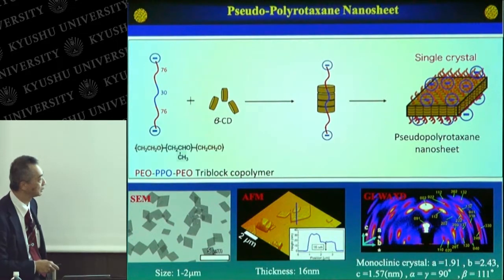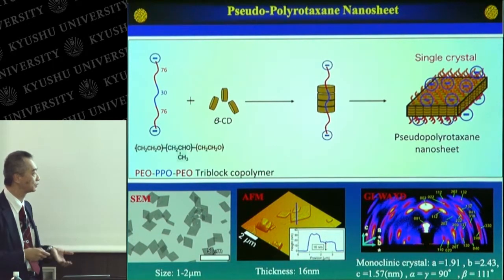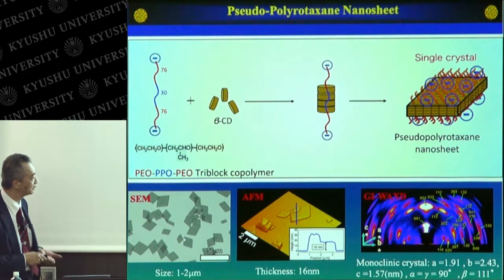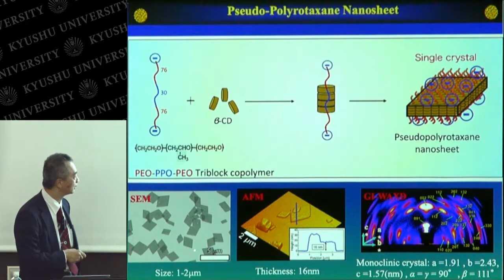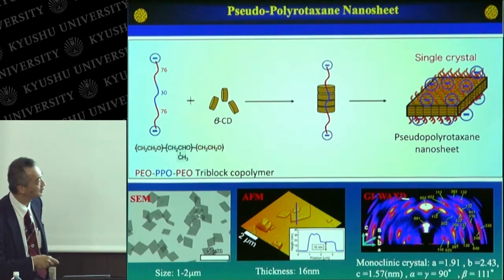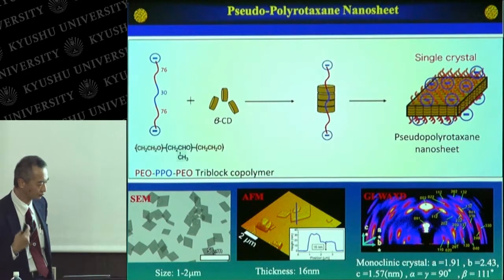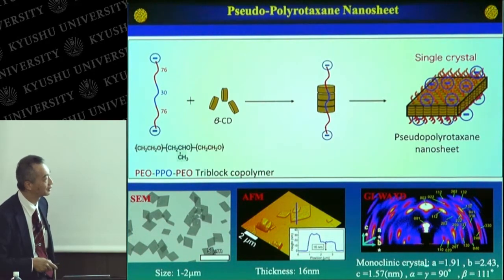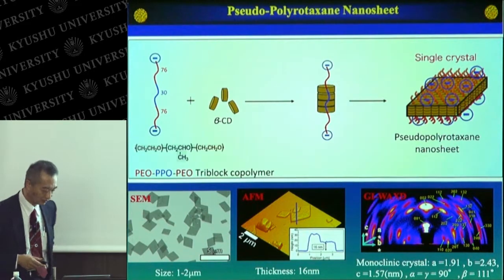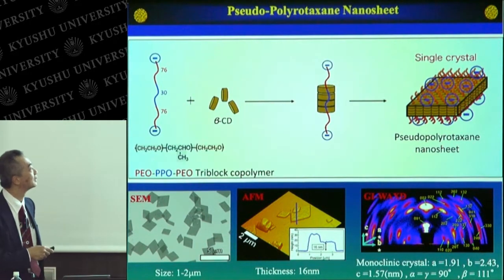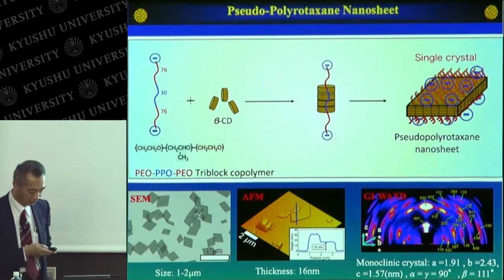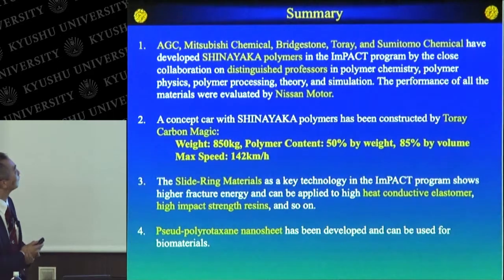You can see that this nanosheet has a thickness of 16 nanometers. It's dispersed in the water, and the size is about 1 or 2 micrometers. And you can see this nanosheet has this shape. So this shows the X-ray diffraction results of this nanosheet. It shows a single crystal, and it's very simple. It's a very complete monocrystal nanosheet.